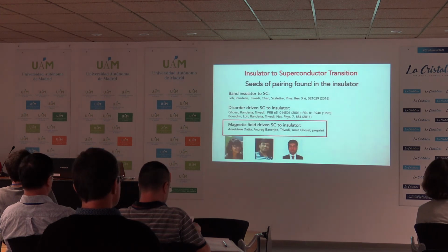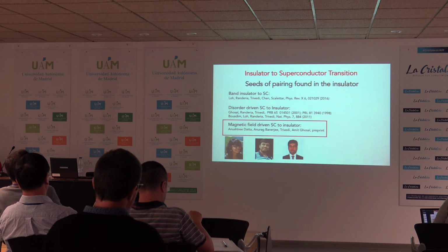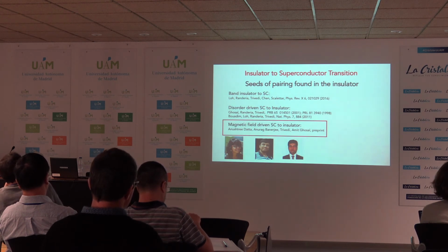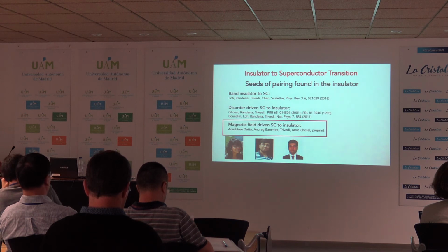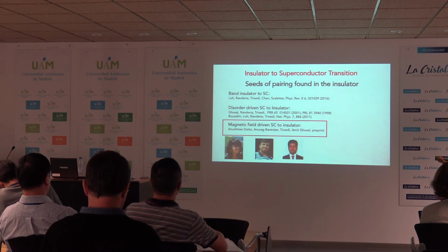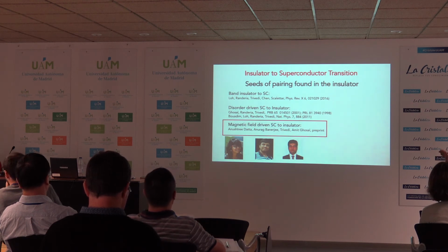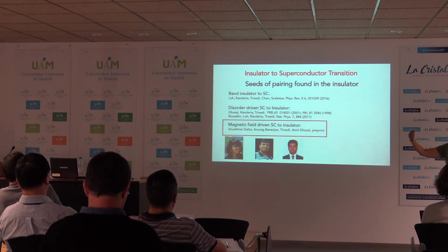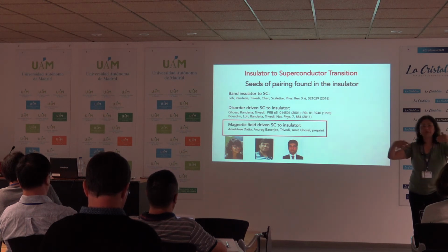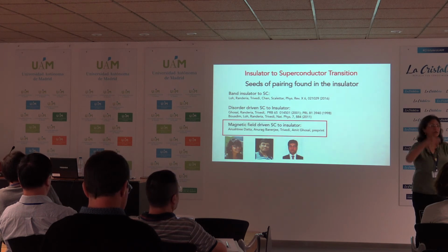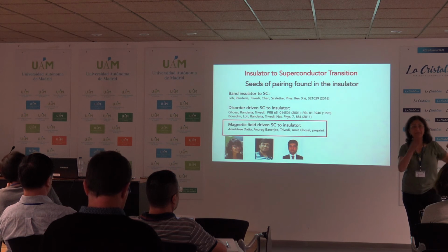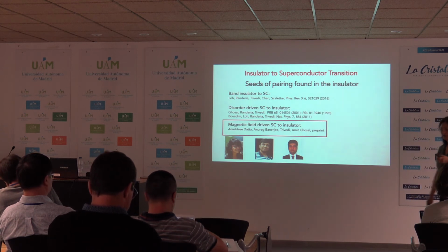Okay, so let me come to the last part, which is the magnetic field-driven transition. Let me just say very quickly in words that if there is no disorder, we have the standard picture of applying a magnetic field and getting vortices. These vortices form a triangular lattice. The core of the vortex is metallic, and at some point, as you increase the magnetic field, the vortex cores overlap and you get a metallic state. So that's the superconductor to normal transition that would happen in a BCS superconductor with Abrikosov vortices.